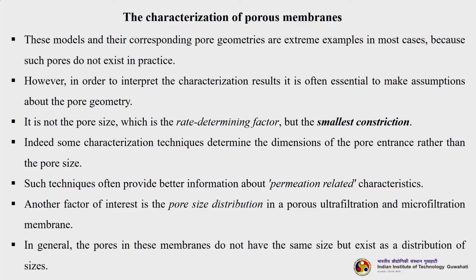These methods, models and their corresponding pore geometries are extreme examples in most cases, because such pores do not exist in practice. However, in order to interpret the characterization results, it is often essential to make assumptions about the pore geometry. Now, it is not the pore size which is the rate determining factor, but the smallest constriction. The pore size we are characterizing is nothing but the diameter of the pore on the surface. But that is not the rate determining factor, and that is not what decides whether a particular solute will permeate through a particular pore or not. What will decide is the smallest constriction inside the pore.